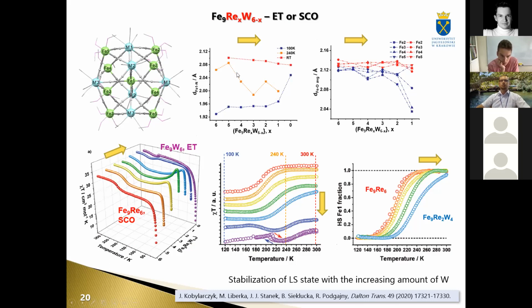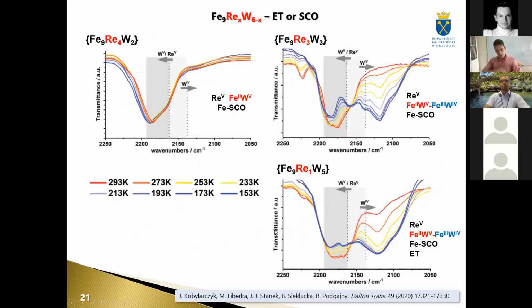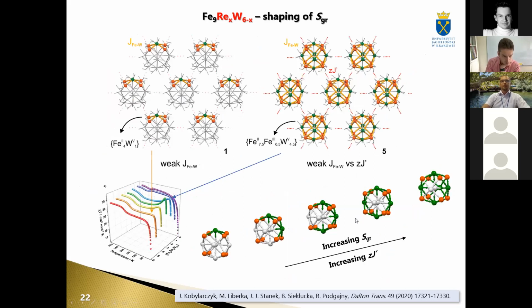Yes, and here are the structural data, iron nitrogen and iron oxygen bond lengths, which are in agreement with the spin crossover in rhenium-rich phases. And only in the tungsten limit, we have something which looks like a combination of preliminary spin crossover with the electron transfer between iron and tungsten. This was also confirmed by the IR spectroscopy, which shows the hump, which is characteristic definitely for tungsten-4 in tungsten-rich phases. So here we have electron transfer, here we have spin crossover. So this definitely shows the difference. Okay, this we can skip.